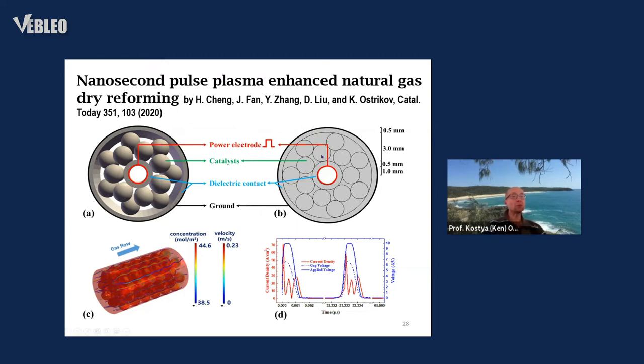And then the space between those little particles is filled by the gas that we are going to reform. And then plasma is excited in those small spaces after we apply some voltage. And the voltage could be applied in very different ways. In this particular example, the voltage is applied in a very energy efficient way using nanosecond plasma excitation, nanosecond pulses that deliver a high amount of energy, but intermittently, and save energy otherwise when you do not need to supply. What happens when you supply this energy and then switch it off?